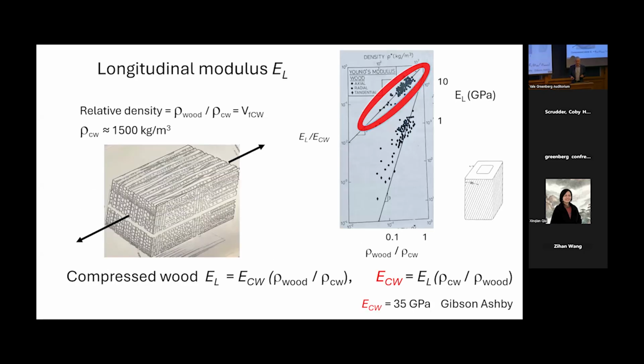Essentially, relative density is a very important concept here. The longitudinal modulus of the wood composite scales with the relative density. So, straightforward: the more tissue you have, the higher the modulus of your material. If you look at this image here, this is data from a large variety of species. If you back calculate the modulus of the cell wall, it ends up at 35 gigapascal. The reason you have some scatter is because of anatomical differences between species, but also the microfibril angle, the angle at which the stiff cellulose fibril is oriented with respect to the longitudinal axis of the cell.